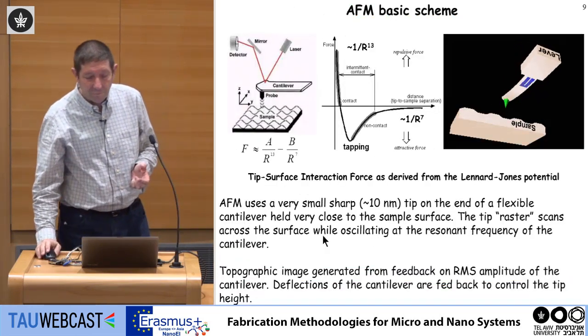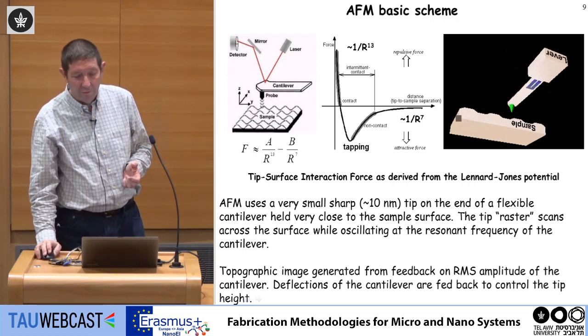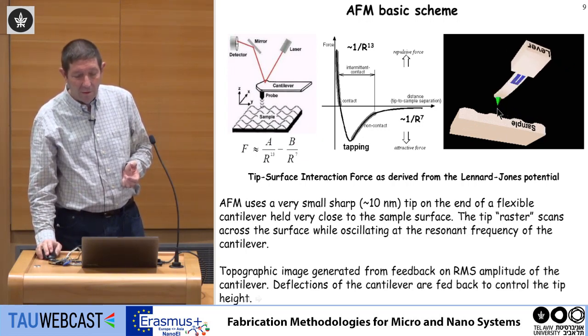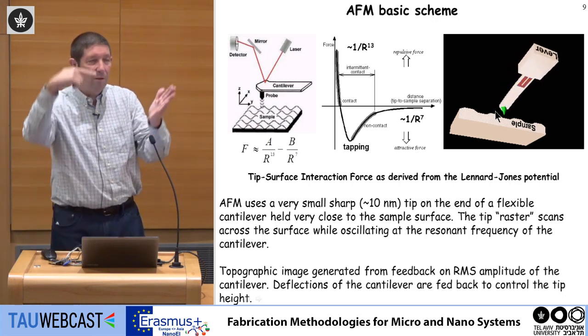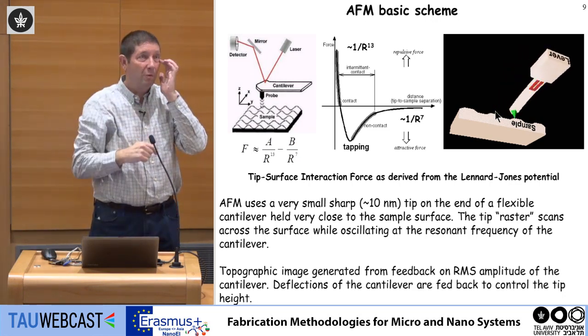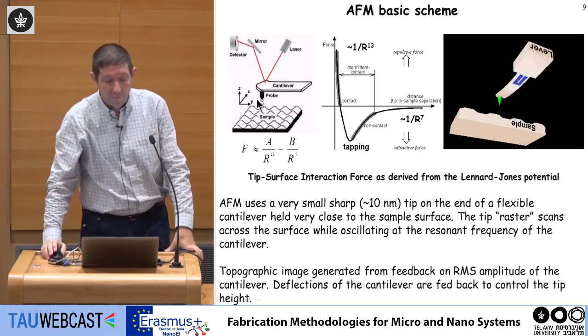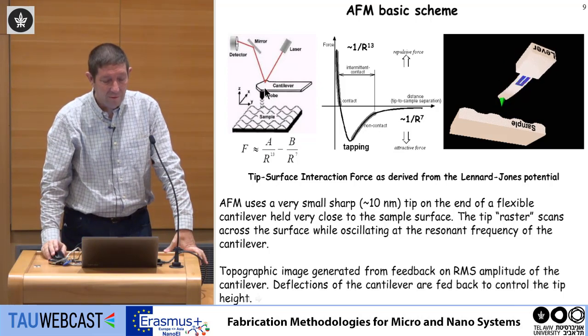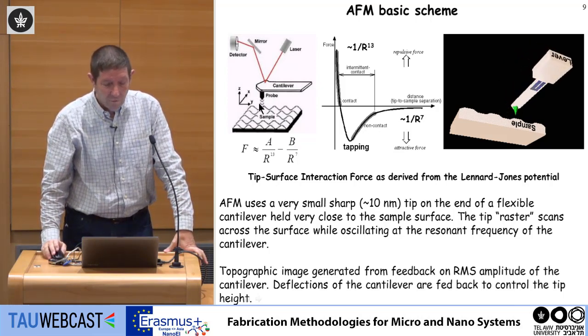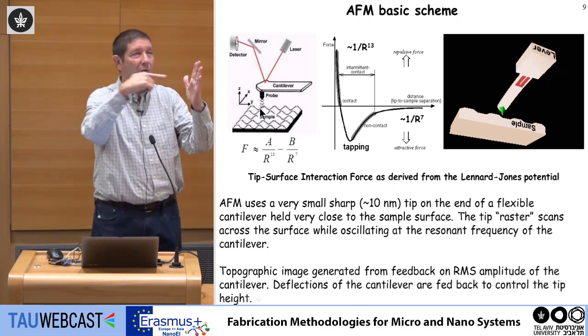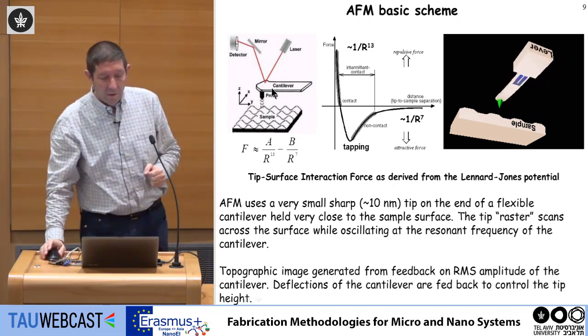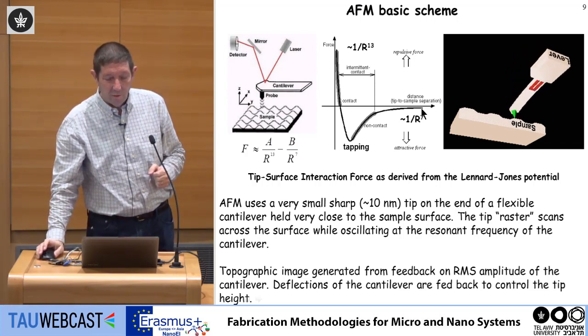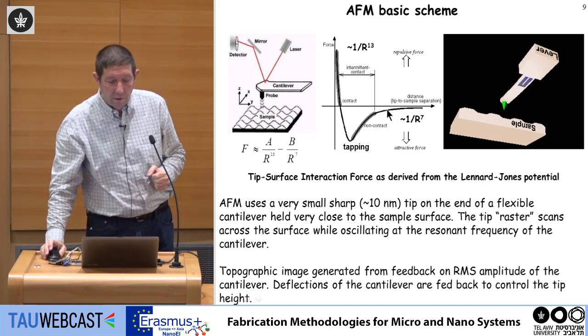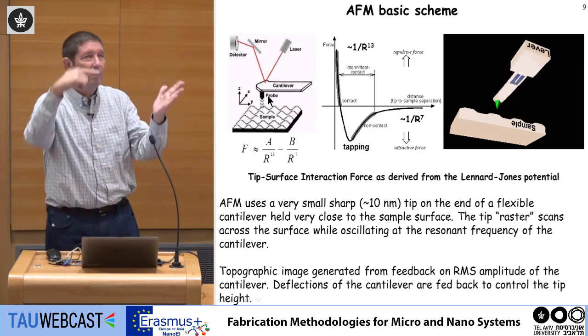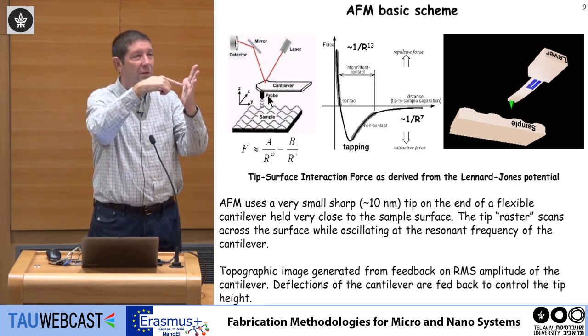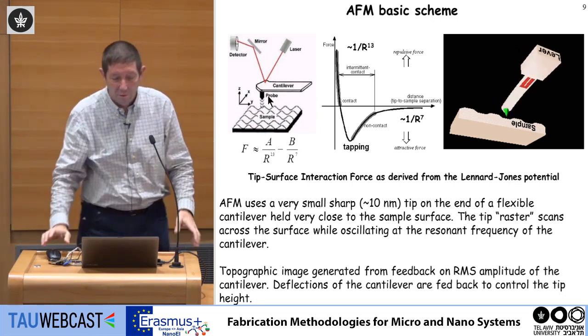So practically, how it works. This is your sample. You take a needle, and you try to move it toward the surface. And if you remember from your introduction to material science classes, if you take a material and try to bring it close to another material, practically there is a point. Initially, you may have some attraction forces between the molecules, but after you reach a certain point, you start to have repulsion forces. So this is what they call the